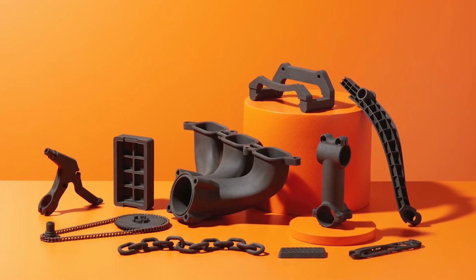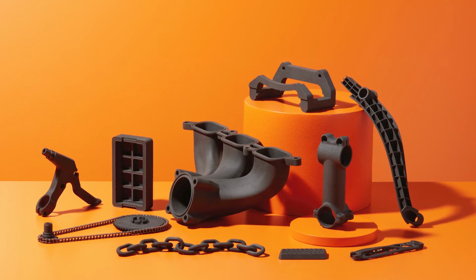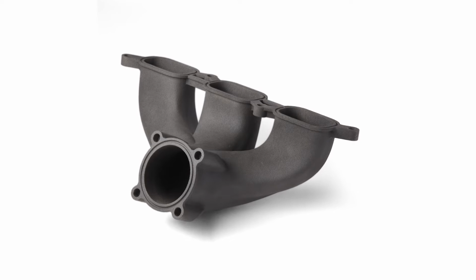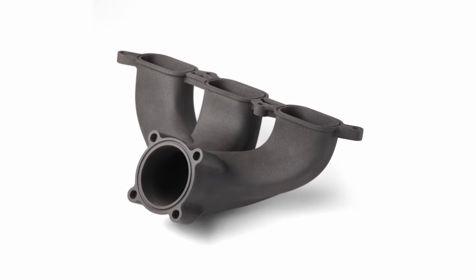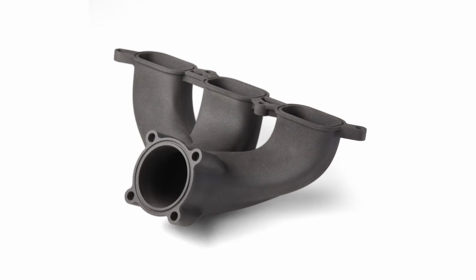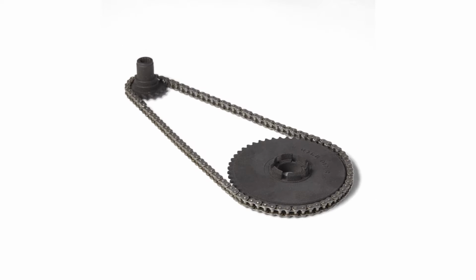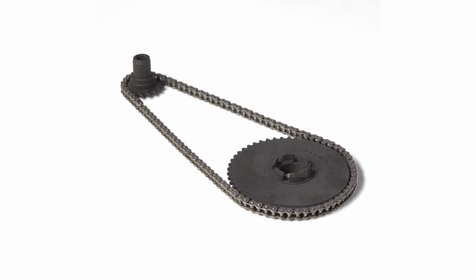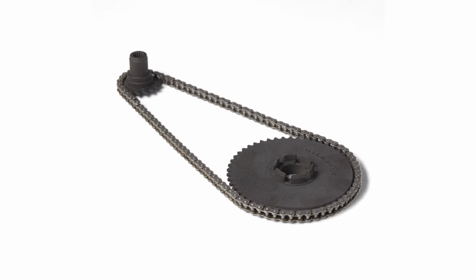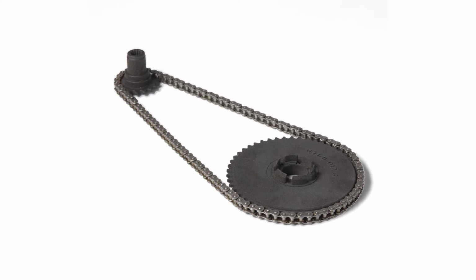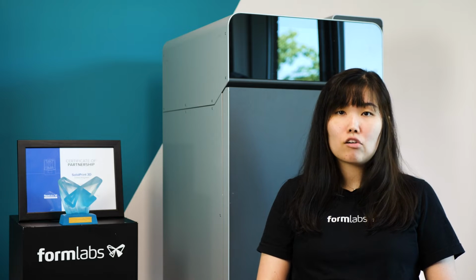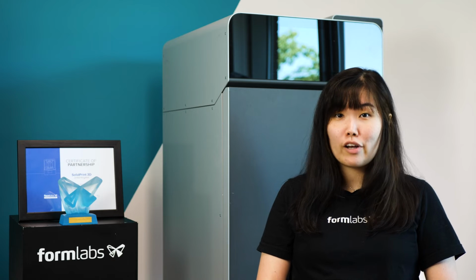Ours is in particles. Essentially, when you are printing with Nylon 11 carbon fiber, the powder is laid down as you do in any SLS, and the roller is placed to essentially flatten out the layer. When that happens, the carbon fiber particles are aligned to the direction of the roller, which does result in a difference in mechanical properties based on which way you orient your part.